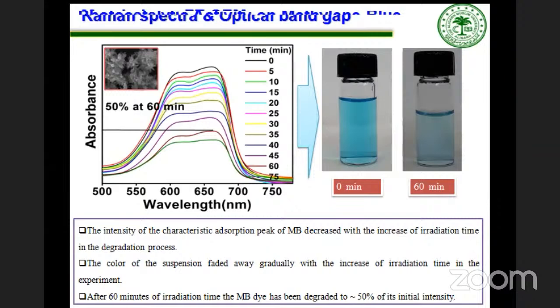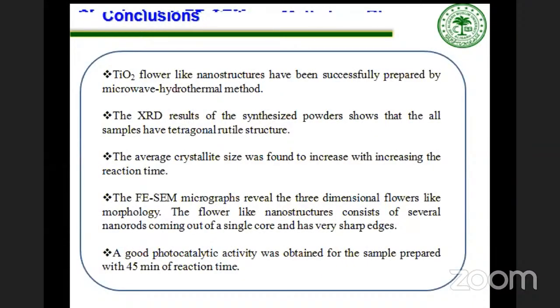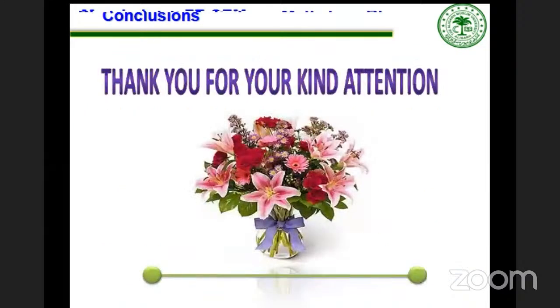It's also clear from the picture, we took pictures of the solution after different time intervals of exposure to the light, and it shows that at 0 minutes it shows the complete blue color, and after 60 minutes this color is degraded. That means the dye is degraded. So it shows that our synthesized titanium dioxide nanorods show a good photocatalytic activity for water purification. Thank you.